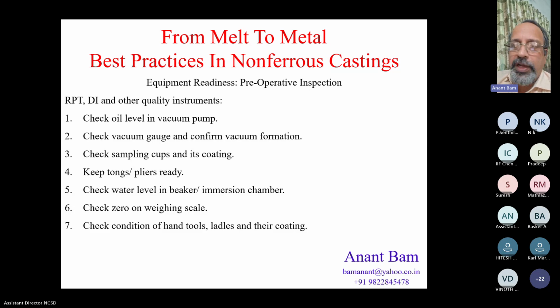The requirement of oil is hardly 300 ml, and the top up required is maybe once in 6 months or so. But if you don't top it up, you lose the pump. Second, check the vacuum gauge and confirm vacuum formation. Start the reduced pressure test apparatus without any metal or sampling crucible within it. Close the lid. See that the vacuum gauge is indicating vacuum.